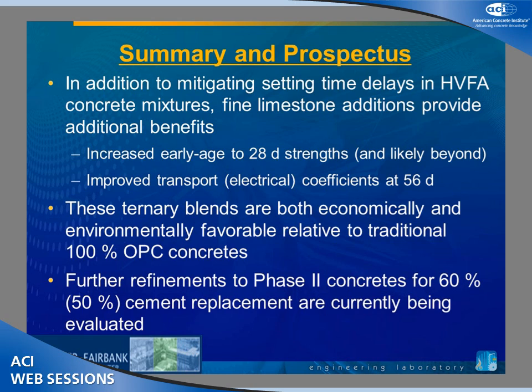We got very high one-day strengths with our Type 3 cement, so we've actually kind of backed off a bit on our cement contents and increased our water-cement ratios a little bit to try another round of those.